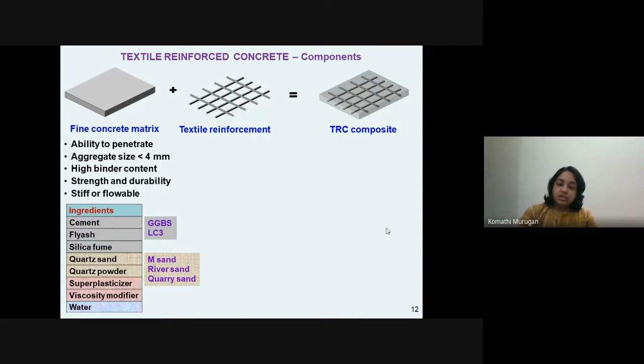Essentially, in our research here, what we use are the cement, fly ash and silica fume as the binder part. The main binders that we use are the cement, fly ash and silica fume. At present, we are also looking at the utilization of ground granulated blast furnace slag and limestone calcined clay cement as replacement for cement, more replacement for cement, in order to reduce the carbon dioxide emissions. And as aggregate, what we prescribe is the utilization of quartz sand and quartz powder in place of the other types of aggregates. But we can also work with the M sand, river sand or the quarry sand depending upon its availability and also depending upon the economy cases.